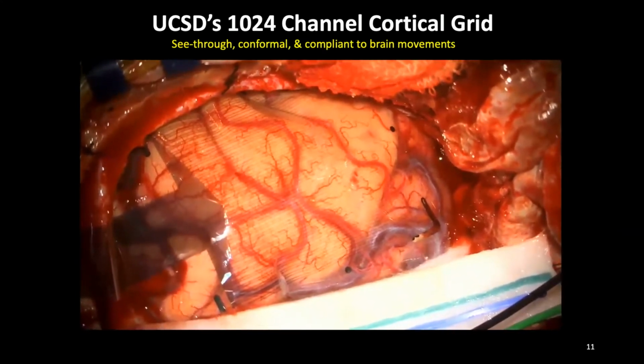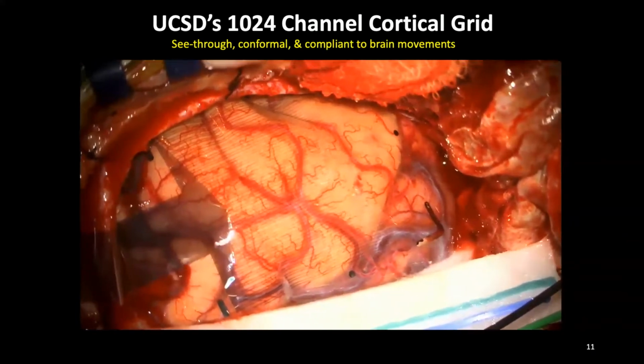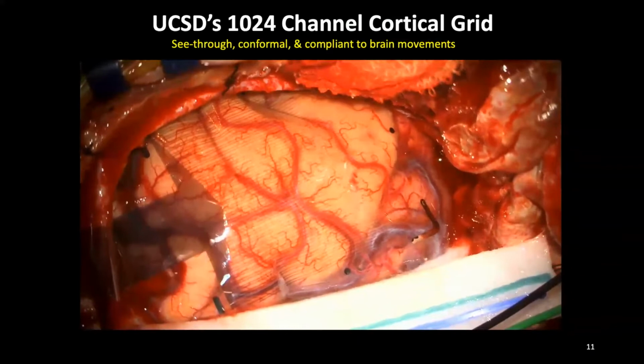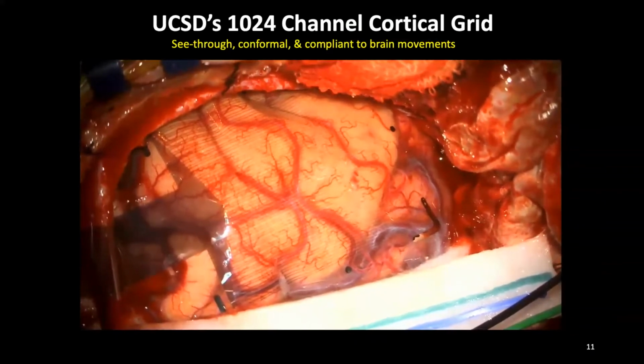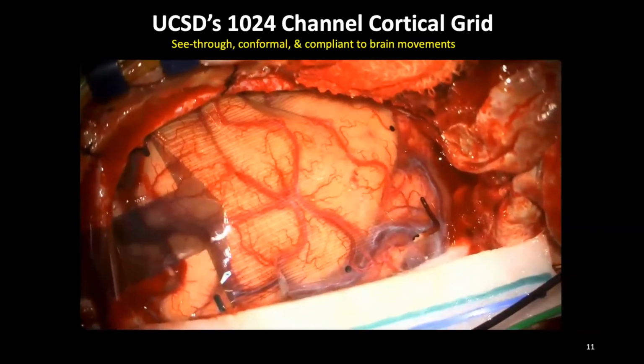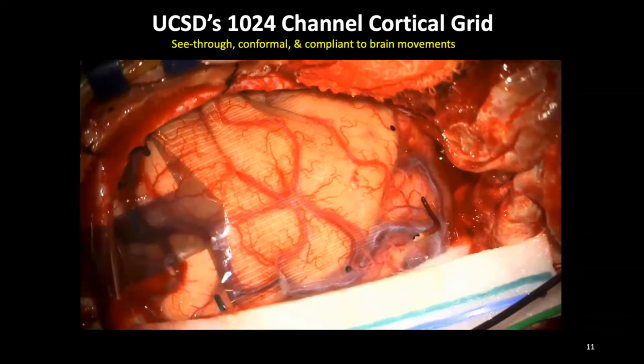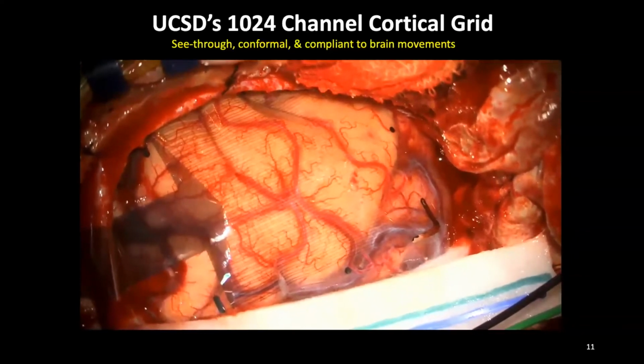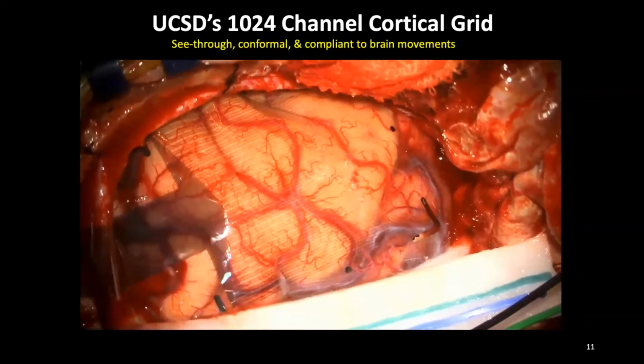This is the 1024 grid placed on the surface of the brain, again, a patient undergoing neurosurgical resection. And you can see that the grid is very conformal to the curvature of the surface of the brain. It's also compliant to the brain pulsation. So you have an intimate contact between the electrodes on the grid and the surface of the brain. You have high recording for a longer duration of time. It's also transparent so that you can correlate the recordings with the anatomy underneath or place it in the right region that you want to do the recordings from.